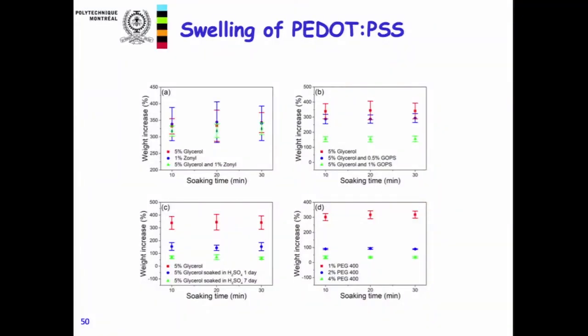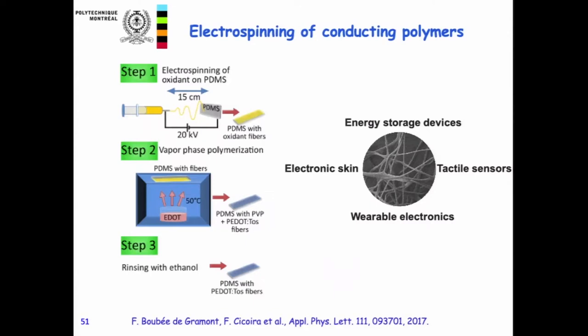So here there are several plots of weight increase versus soaking time for different formulations. So we changed the surfactant, the polymer. And you can see that actually there is a quite large swelling for each of these formulations. And this can in part explain why, when you add water, you have this healing. But still, they don't explain it because for some systems, you don't need water. And we are still working on this. OK, I think I used almost all my time.